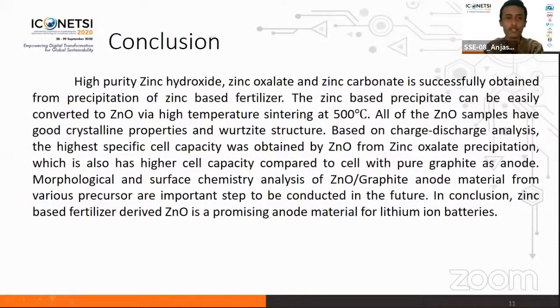High purity zinc hydroxide, zinc oxalate, and zinc carbonate were successfully obtained from precipitation of zinc-based fertilizer. The zinc-based precipitate can be easily converted to ZnO via high temperature sintering at 500 degrees Celsius. All of the ZnO samples have good crystalline properties and wurtzite structure.